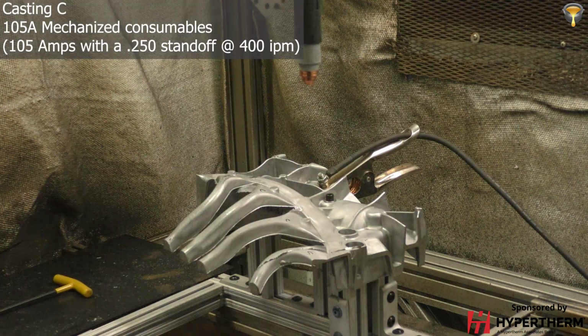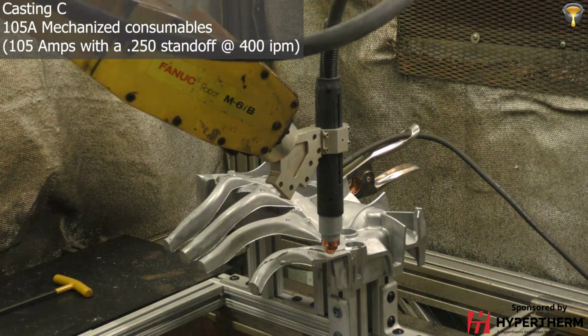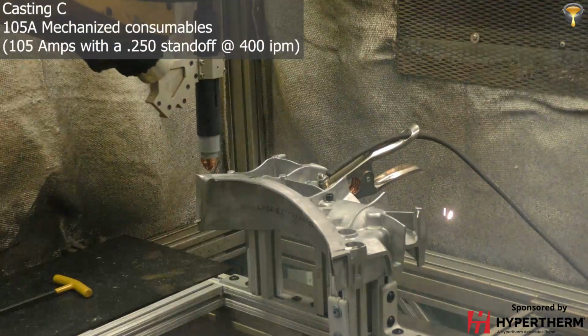That's why we're recommending the PowerMax 105 SYNC for these applications to our customers. That seems to be the best well-rounded. Taking out 1 meter length of flash, how fast can you do 1 meter? I think when you're talking less than 10 millimeter thicknesses, you're probably around 2,500 millimeters a minute.